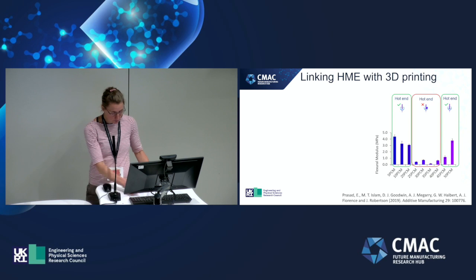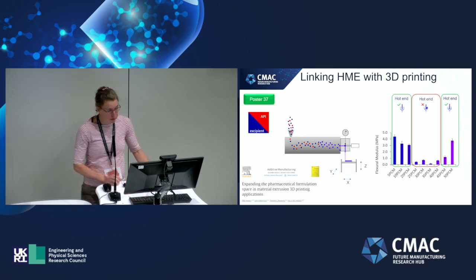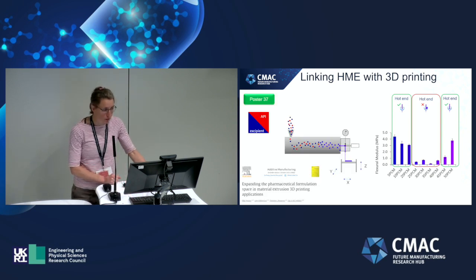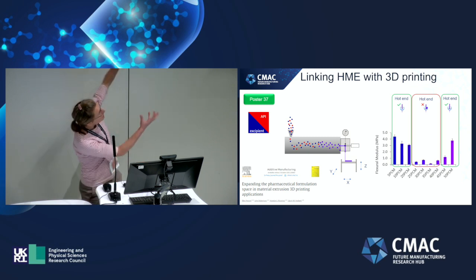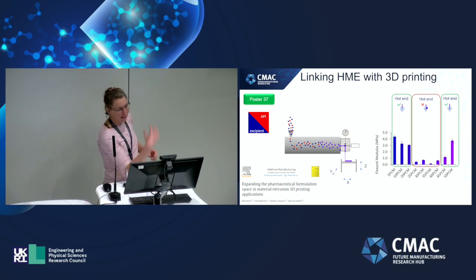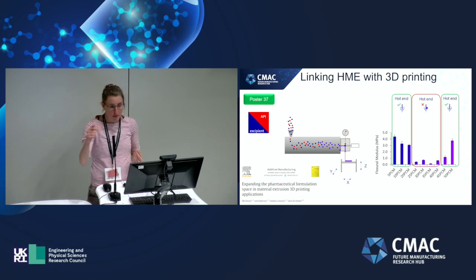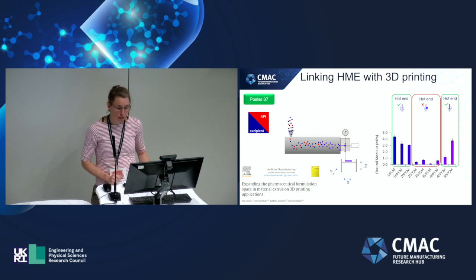So it was just the ratio of API to polymer was plasticizing the system so much that this just wouldn't work. So in-house, we've developed a 3D printing microfactory where we linked a small-scale hot melt extruder, an 11 mm extruder, which is the big gray box on the left, and then at the end we've bolted on a dosing device that allows us to print directly from the melt state of the material onto a print bed. So this obviously opens up the pharmaceutical formulation space, because we were able to print all these formulations that we were previously not able to print because of the unfavorable properties.